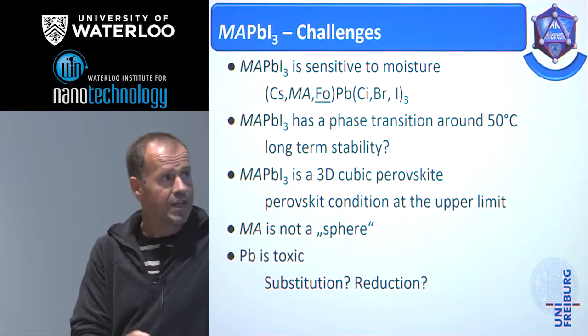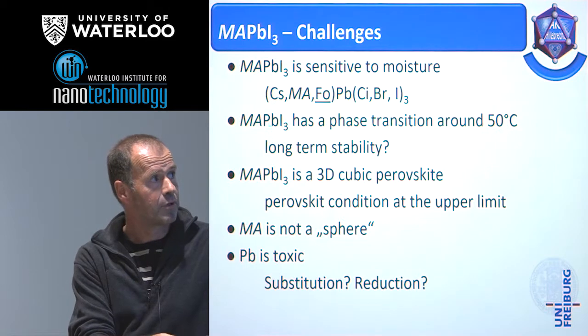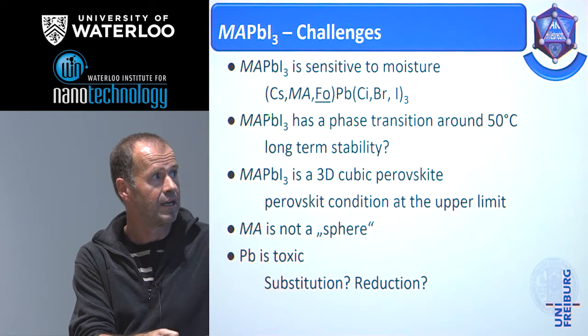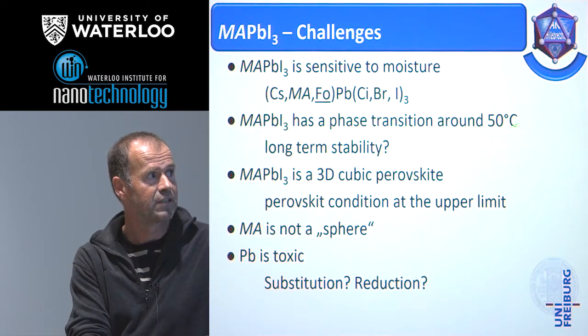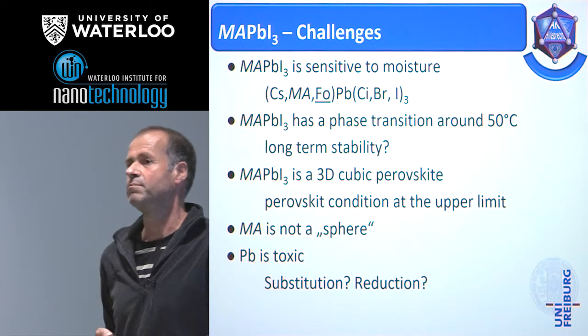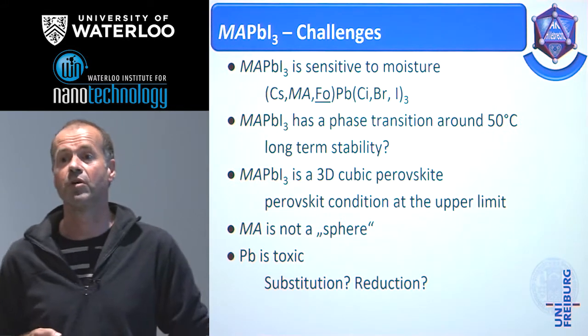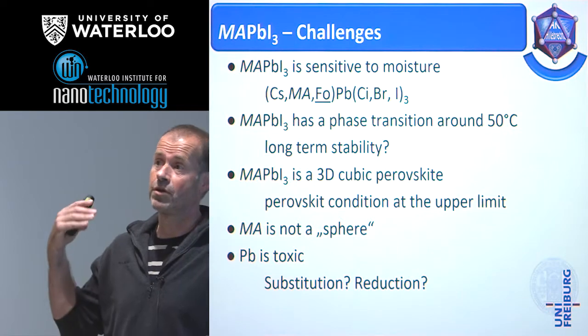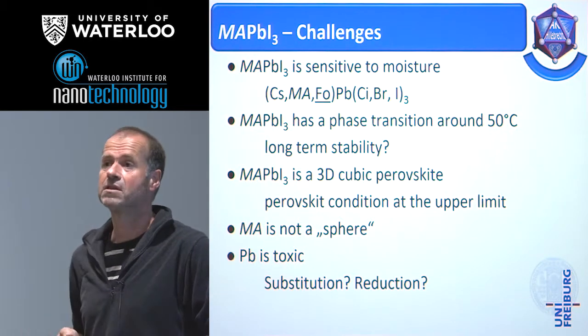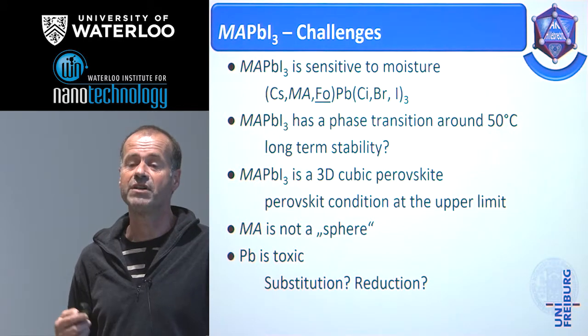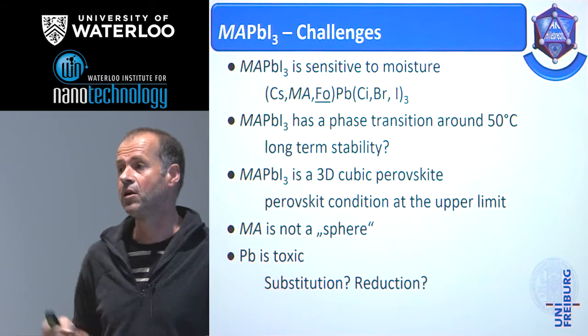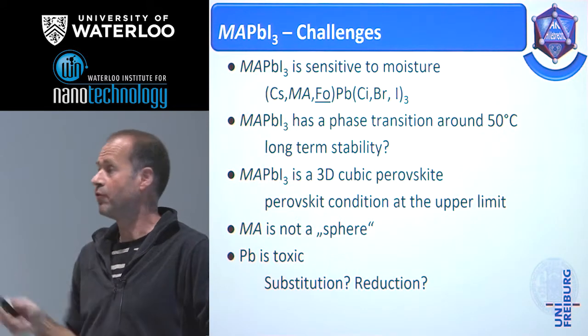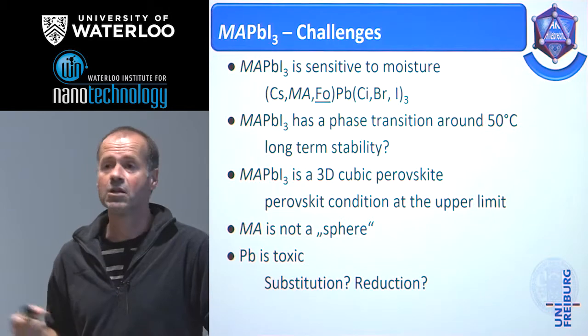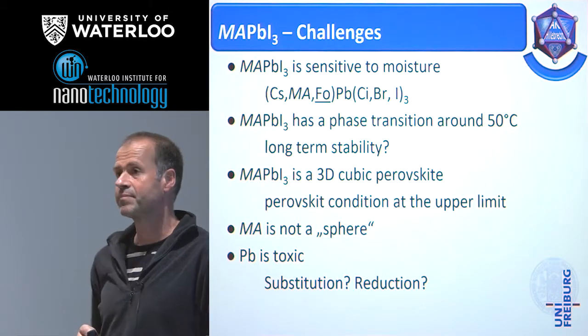Then there is a phase transition of methyl ammonium lead iodide around 50 degrees Celsius, and that's a problem because these are temperatures which are reached during the use of the solar cell, and that means you have an inherent instability of the microstructure of your layer, and it would be good to be a little bit outside.